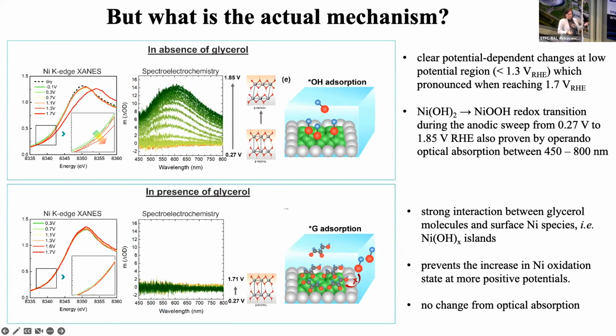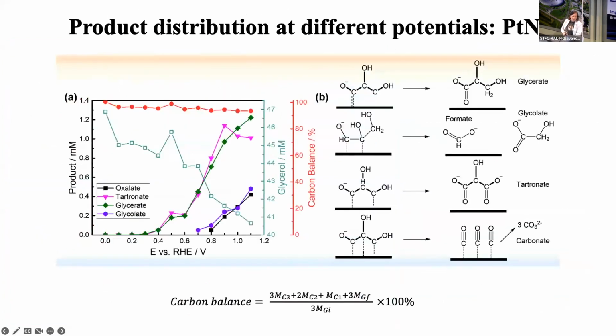And we also did some FTIR, but there's a bit too much to show. Now, what are we making on this? So it seems this works the best. So we look at platinum nickel 2, and it seems that we actually make C3 products, which is glycerate and tartronate, at low potential, and then we have C-C cleavage at higher potential to make glycolate and oxalate, which you can't determine by HPLC, but we've seen it by FTIR, and you could see how the glycerol concentration is going down.